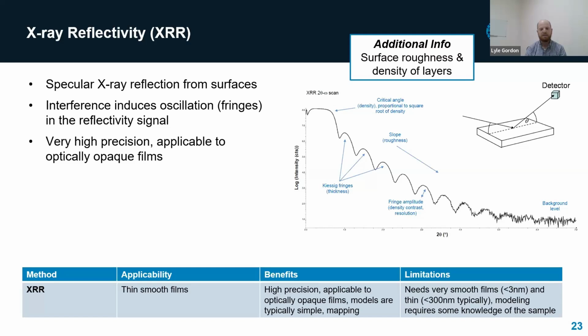In some ways, there are some similarities with ellipsometry. So we're looking at the specular reflection of X-rays at shallow angles from about 0 to 8 or 10 degrees from the sample. And the interference between the thin layers in the film results in interference fringes. And these are very sensitive to the film thickness over a range of a few to maybe 200 nanometers. And I'll show you some plots like what Max showed. So this is really applicable to thin, smooth films. It gives you really high precision, accurate measurements of the thickness. And I'll talk to you about some of the limitations.